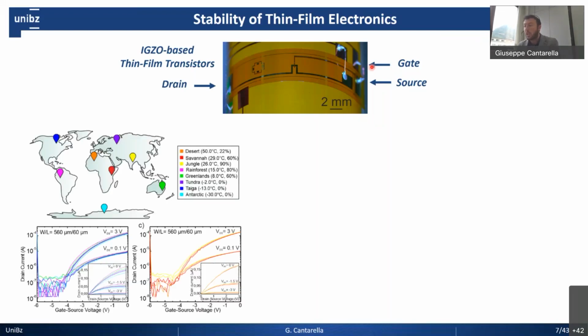So what she did, as you can see on the left-hand side of the slide, is simulating the most extreme climate zones on our planet using a climate chamber. She simulated, for example, very high temperature zones, such as the desert at 50 degrees with a humidity of 22%, down to low temperature areas, such as the Antarctic, at minus 30 degrees and no humidity. And the idea was to monitor the performance of our transistor.